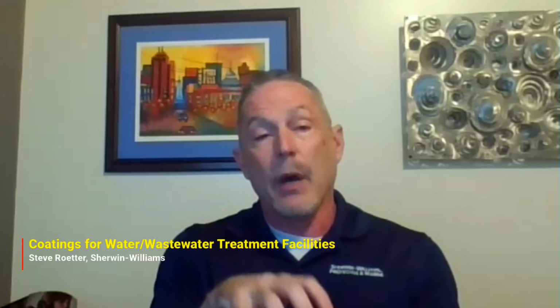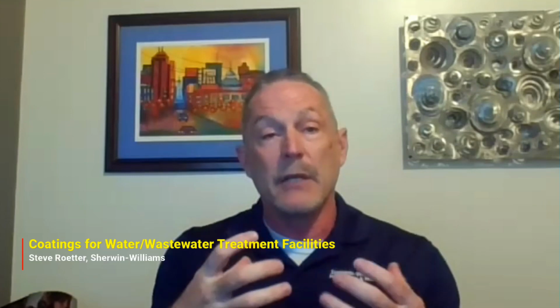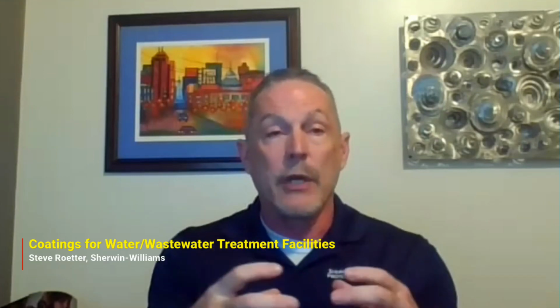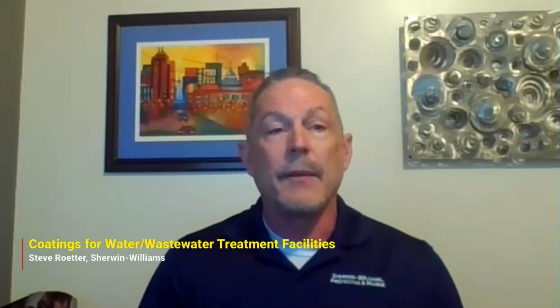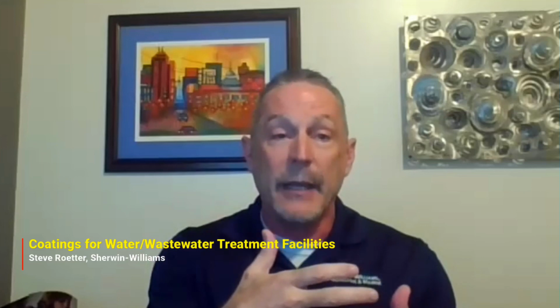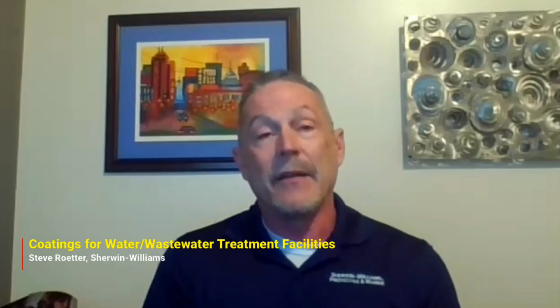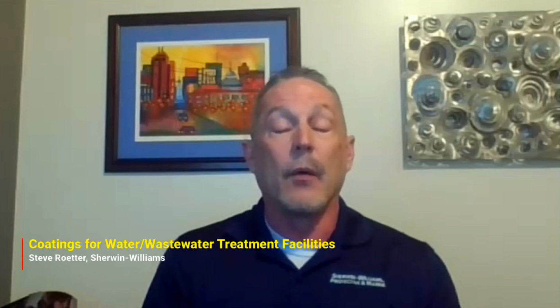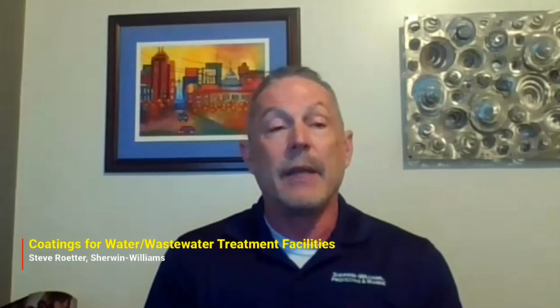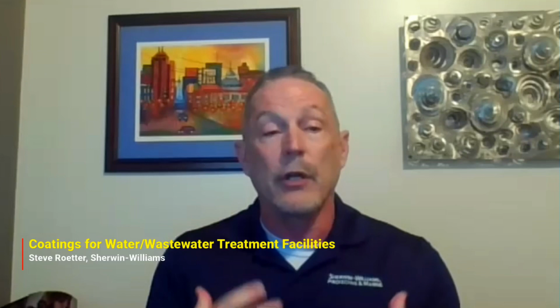And these products that are created in this process have a higher volume than the original components that created it. So as they expand, you get microcracking of the concrete, which starts to deteriorate even further, but the cracking also allows deeper penetration of the sulfates into the concrete, and it continues the attack even deeper. So it's sort of self-perpetuating as long as you have the moisture there. Those expansive forces are really the problem.